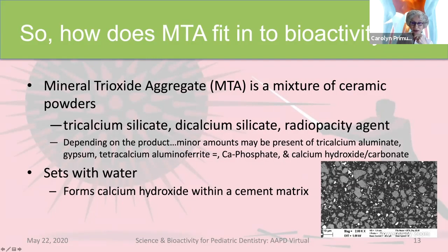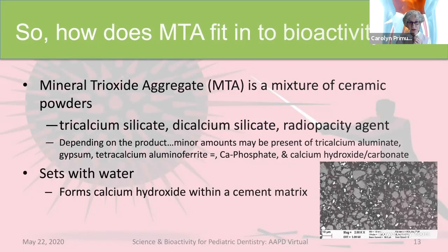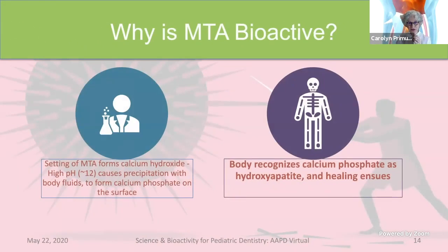These light gray areas are the cement particles, and they're surrounded by a darker gray matrix in which the calcium hydroxide is present, and the hard part of the hydrated silicates. The little white bits that you see in this SEM photograph are the radiopaque powder that's dispersed with the other cements. So we create a hard matrix.